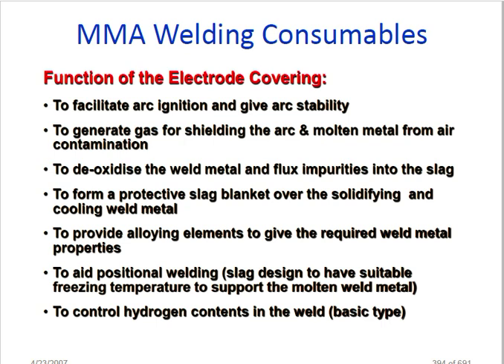What are the functions of the electrode covering? To facilitate arc ignition and give arc stability — if the flux is there, the arc will be stable. To generate gas for shielding the arc and molten metal from air contamination, so no atmospheric contamination will occur. To deoxidize the weld metal — the flux prevents oxidants from going into the weld metal. To form a protective slag blanket over the solidifying and cooling weld metal.